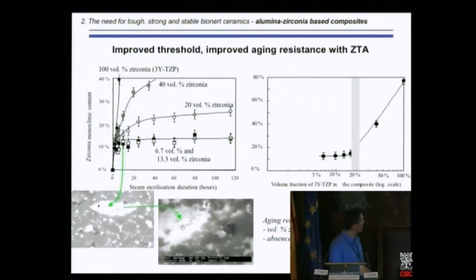I just want to emphasize these two graphs, in which I have an alumina zirconia composite with quite large zirconia aggregates. Unfortunately, with this composite, you will have aging of these aggregates. So if you process an alumina zirconia composite, you will need a perfectly homogeneous dispersion of these zirconia particles inside the composite. If not, you will have aging of the zirconia aggregates. This is before aging, not the same aggregate, and after aging, this zone has been degraded by aging. So alumina zirconia composites can be a first answer to toughness, strength, and good stability.